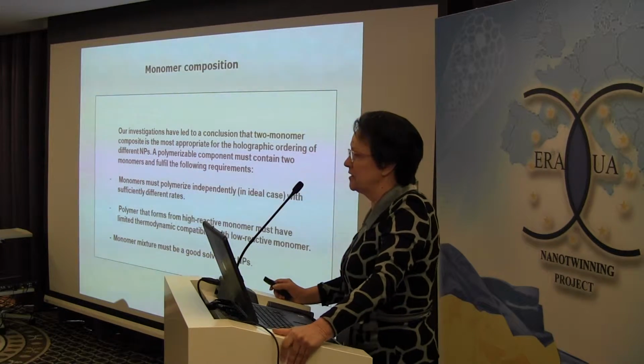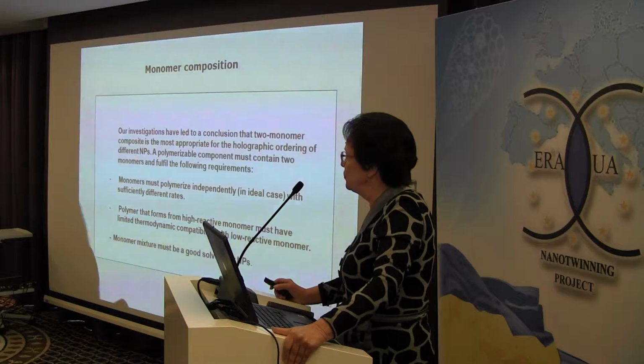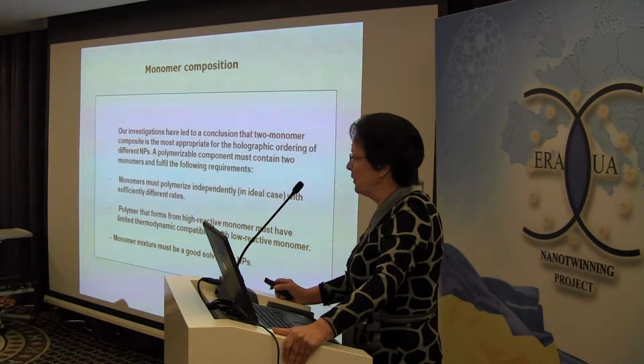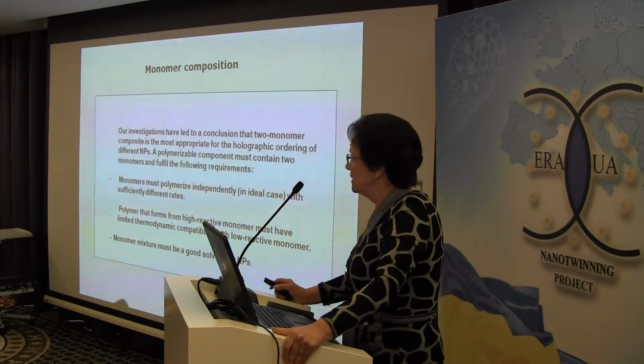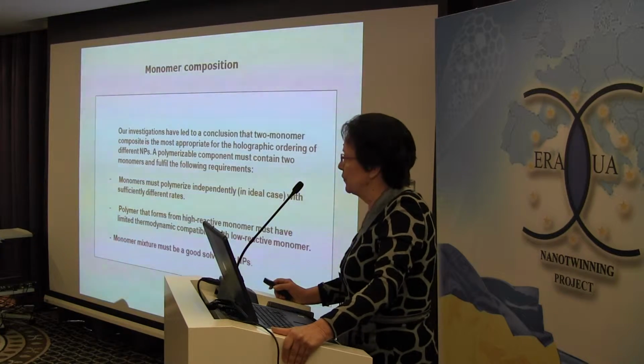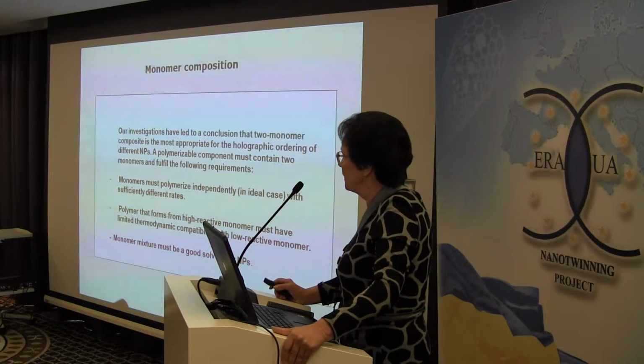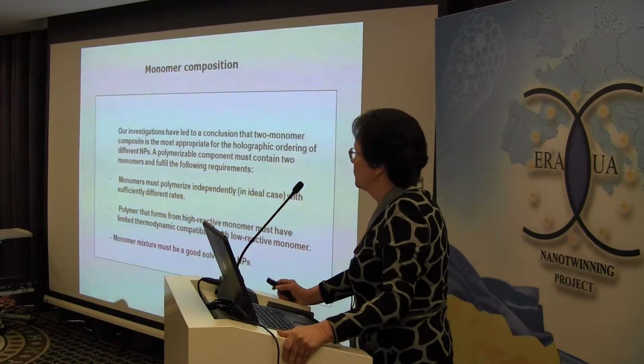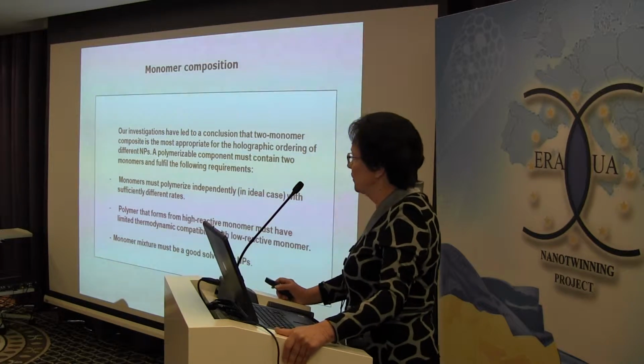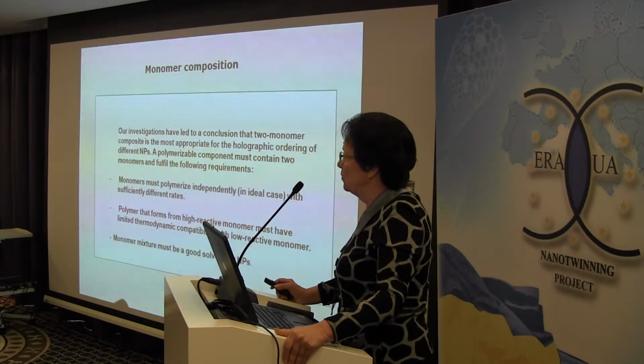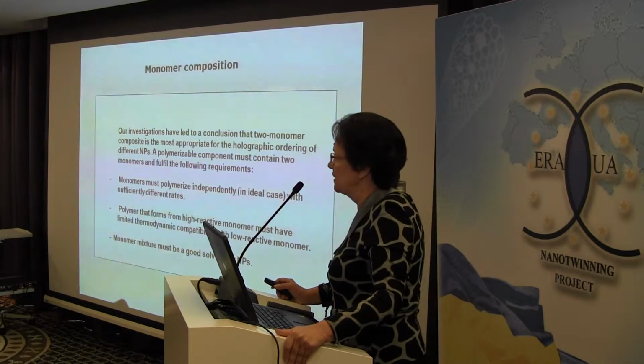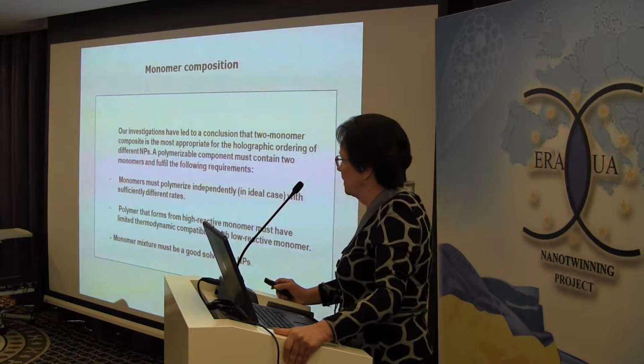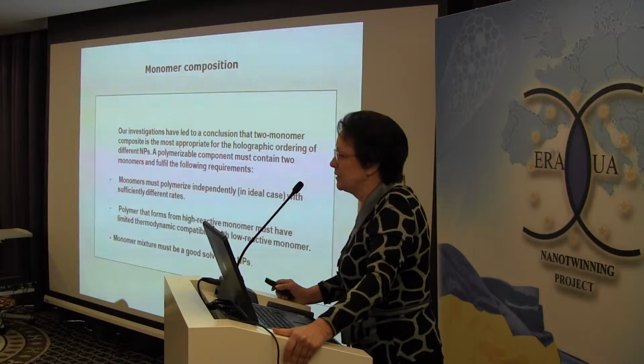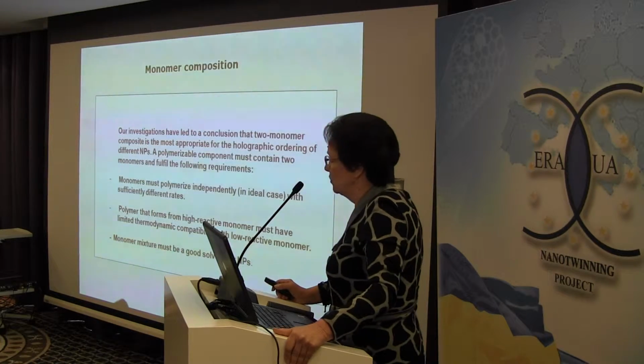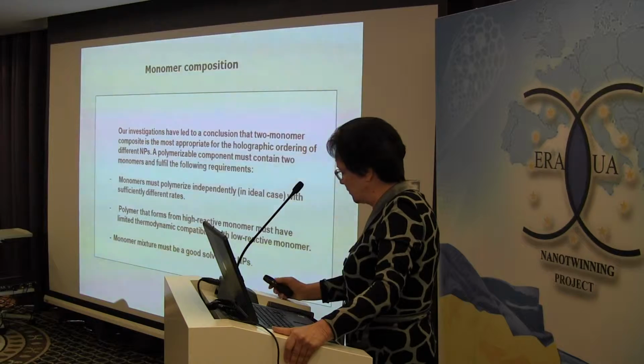Our investigations led to the conclusion that the two-monomer composite is the most appropriate for the holographic ordering of nanoparticles. This mixture contains two monomers that must polymerize independently with different rates, and this mixture must be a good solvent for the nanoparticles.